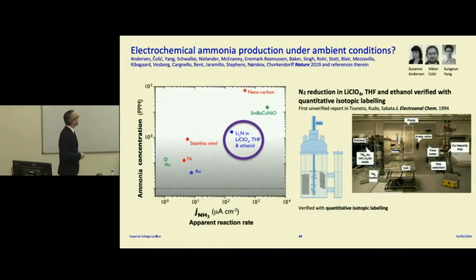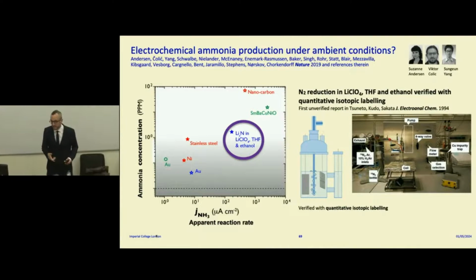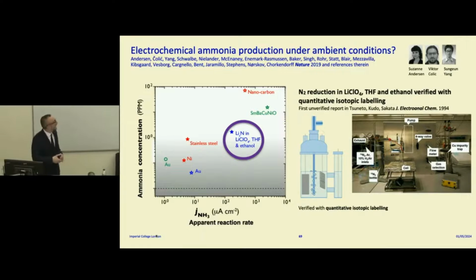So in my old research group, we looked for years and years and years to try and make ammonia using electrochemistry, and we failed really miserably for many years. But lots of reports in the literature started saying they could do it. So we set up a protocol saying, if we were to make ammonia, this is how we would prove it. And what we found is that a lot of the reports in the literature, which were reporting such small amounts of ammonia, were actually looking at contamination from the lab environment. So it was actually all nonsense, in fact.